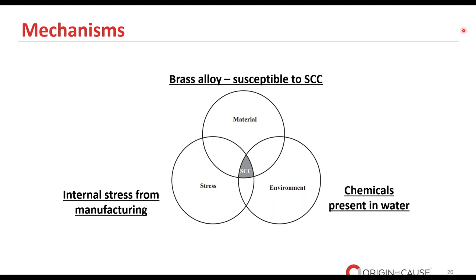Now, diving into the mechanisms that might be promoting SCC, a combination of material properties, environmental factors, and manufacturing practices come into focus. At the forefront is the intrinsic property of our material in question. The brass alloy, by its very nature, is susceptible to SCC. And this material vulnerability sets the stage for potential degradation, especially under specific conditions. Compounding this is the presence of chemicals in the water. As our earlier findings suggested, even low levels of certain chemicals can dramatically increase or accelerate the SCC process. And given the water's composition, there's a heightened risk of interaction with brass promoting corrosion.